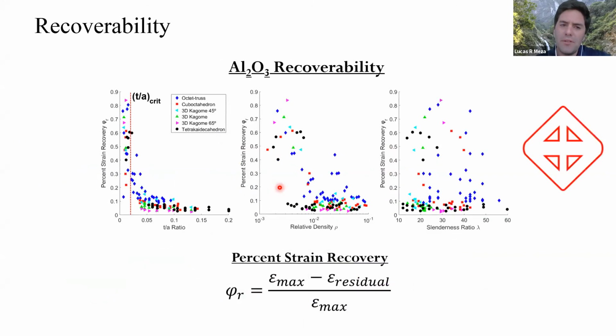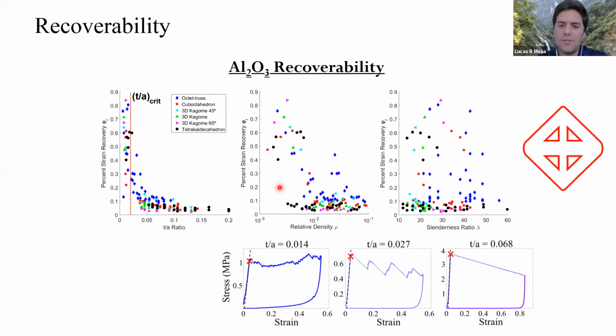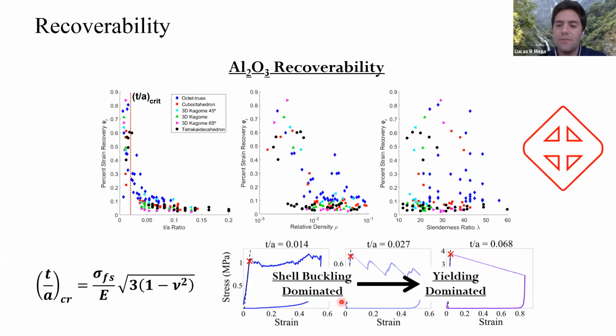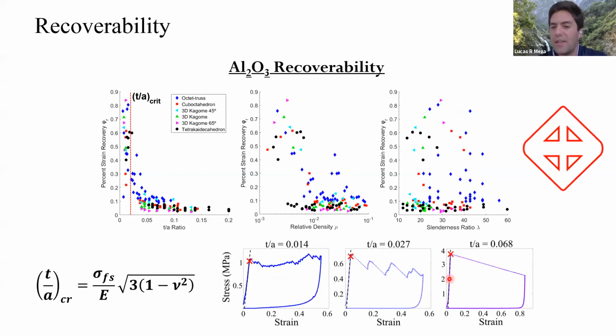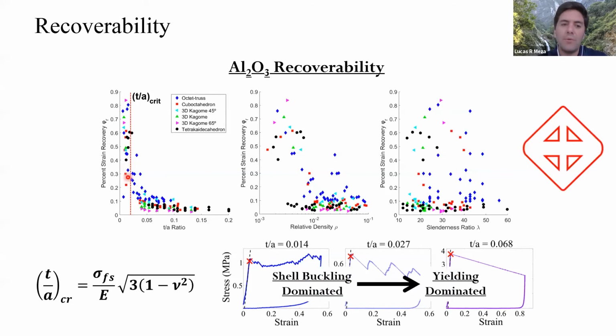When we looked at shell structures, you again have that T over A critical ratio, that shell buckling versus yielding transition - here shell buckling dominated behavior, here yielding dominated behavior. We saw that at that T over A critical transition, we were able to drastically increase our recovery. So it doesn't really depend on density, it doesn't really depend on slenderness - it very strongly depends on the aspect ratio of the shell wall.